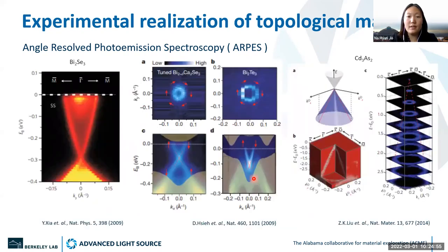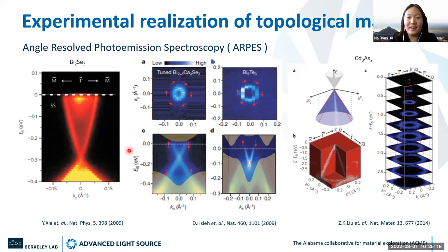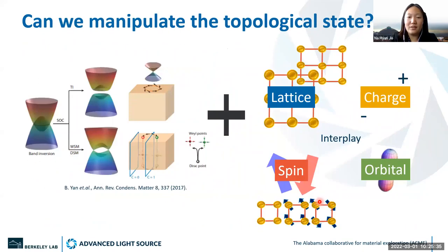These are the experimental ARPES results. You can clearly see the bulk conduction band and bulk valence band, and in between a linear band — which proves it is indeed a topological insulator. After several years of study, we now know that many other systems also show this linear topologically non-trivial feature.